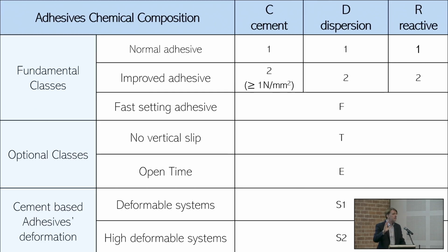is the strongest adhesive you can find on the market because it's not cement, it's made of resin. Epoxy resin, polyurethane resin. Epoxy polyurethane resin can fix anything onto anything. For example, you need to fix tile onto metal. I cannot use cement because cement doesn't fix on metal. I need to fix tile onto plastic, PVC. I cannot use cement because cement doesn't fix on plastic. Only reactive adhesive can do that.